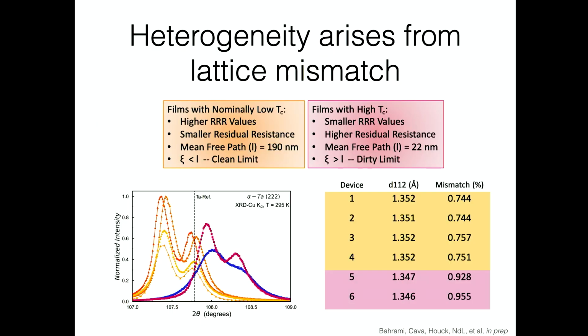So just to summarize, what we find is that the films with this kind of bad AC loss behavior are actually the cleaner films. So these are in the clean limit. And then the films that look like they have a nice high TC are in the dirty limit. So the story here is, we were trying to get rid of two-level systems. We tried to make these films as good as possible, made single crystal, extremely low defect density, all of that stuff. And we accidentally induced a new source of loss.